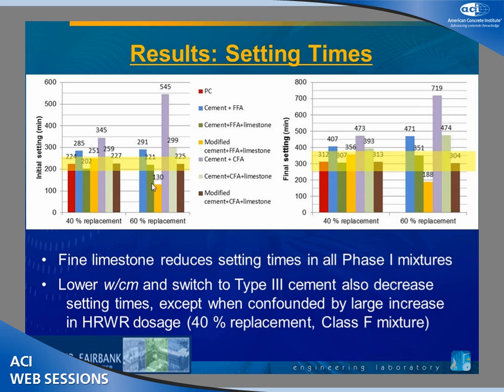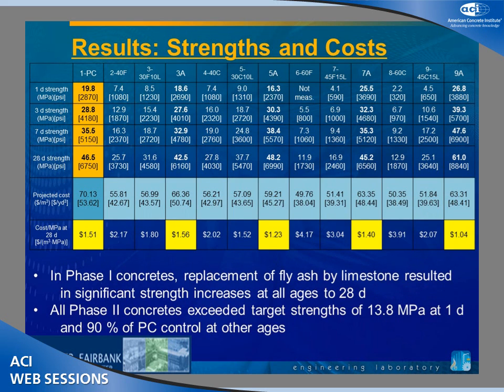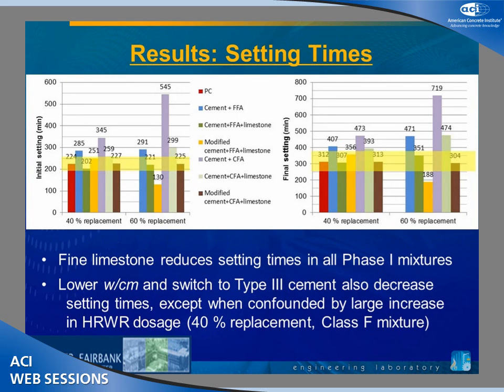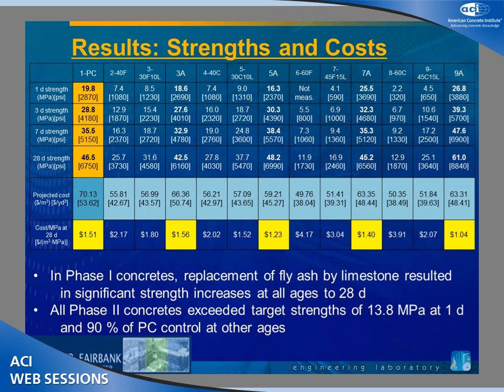The only one that falls a little bit out is one of the phase 2 concretes here. It has a setting time of 130 minutes. That's the one where we have the type 3 cement also contributing to the reduction in the setting time. So in the phase 1 concretes, we were able to get all our setting times back into the range that we wanted, and for the most part, other than the 130-minute one there, they were all maintained through phase 2. So let's look at some of the other properties in terms of strengths.